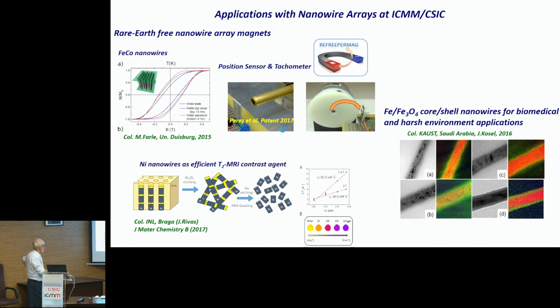Well, some other, in collaboration with Pepe Rivas in Santiago de Compostela, in the Institute of Nanotechnology in Braga, we developed with them, or actually they were using our nanowires as T2 magnetic resonance imaging contrast agents. So the response was very nice. The problem is to get an amount large enough to be detectable, because it's much easier to prepare nanoparticles in a big amount compared to nanowires.